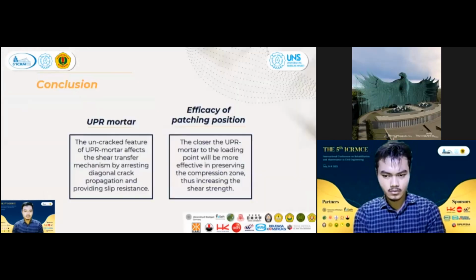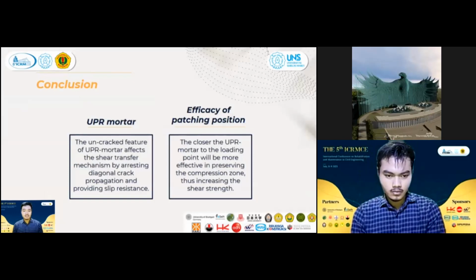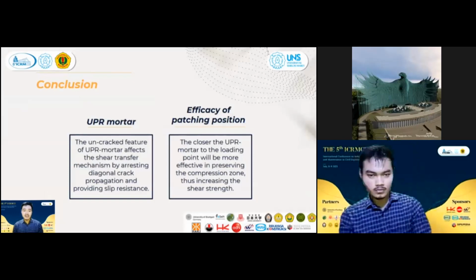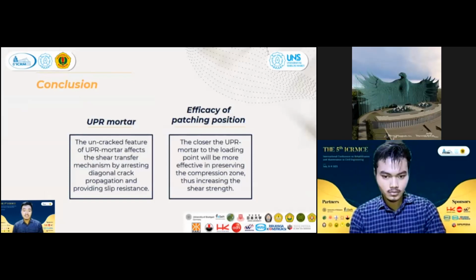Next, conclusion. First, the uncracked feature of UPR mortar affects the shear transfer mechanism by arresting diagonal crack propagation and providing slip resistance. Second, the closer the UPR mortar is to the loading point, the more effective it is in preserving the compression zone, thus increasing the shear strength.